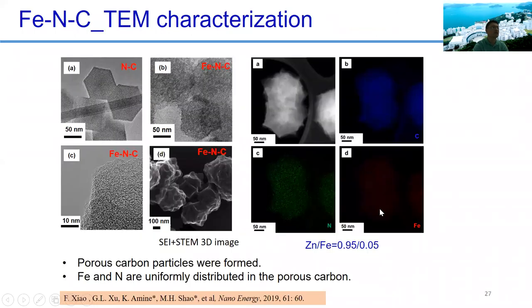And here are the TEM images. This is without the iron doping, a very well-controlled nitrogen-doped carbon particle. This is with iron doping, so it's more porous. If you look at the 3D image, it's a very rough surface, giving you the high surface area to host the iron.